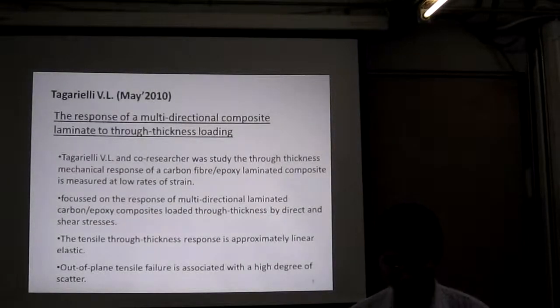The response of multi-directional composite laminate to through-thickness loading. This research studied through-thickness mechanical properties. The mechanical response of the carbon fiber epoxy laminate composite was measured at low rates of strain, focusing on the response of multi-directional laminate carbon epoxy composite loaded through thickness by direct and shear stresses. The tensile through-thickness response is approximately linear elastic. Failure occurs at the ply interface by unstable propagation of an interlaminar crack.